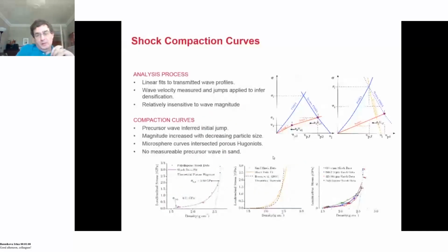So from this, we can start looking at shock compaction curves. There are different levels of difficulty of analysis you can undertake in these kinds of systems. So we use a linear fit in the first case just to help us in the system. We know there is a double jump in the system, so hence we have this particular line here because we know when that jump occurred from the traces. We can then work back into developing compaction curves, and what we have here is this initial change followed by the compaction.